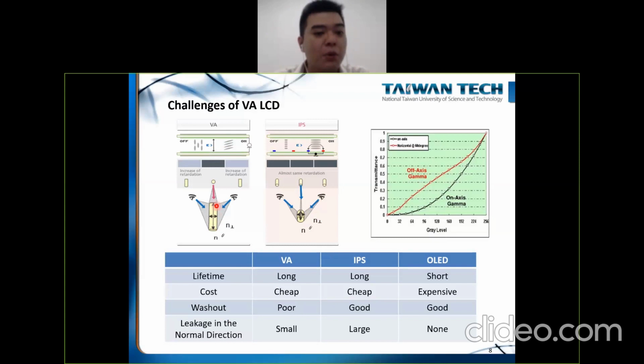normal viewing direction, okay? But for high angle, if you see this liquid crystal display from a large angle, actually you see the short axis of this liquid crystal, okay? And the long axis and the short axis provide different transmittance for the cell. So, for example, for this type of liquid crystal, the transmittance for the long axis will be lower than the transmittance when you're viewing at the short axis. Okay, so the problem with this type of orientation is that when you're looking in the large angle direction, you will see a severe light leakage problem. So the contrast ratio will be significantly dropped when you're looking in the large angle direction.